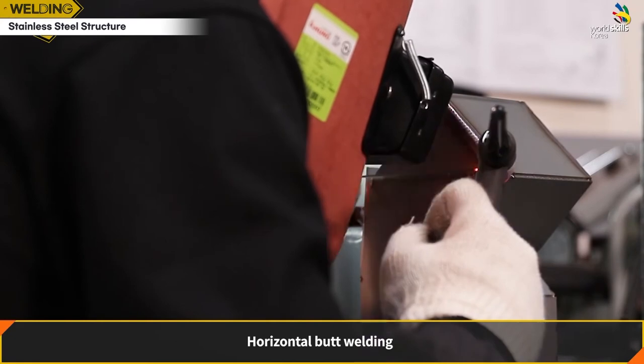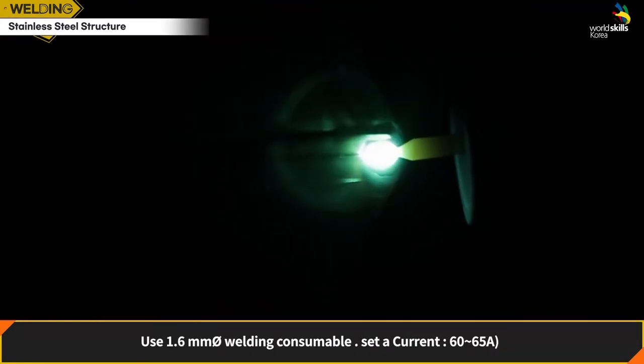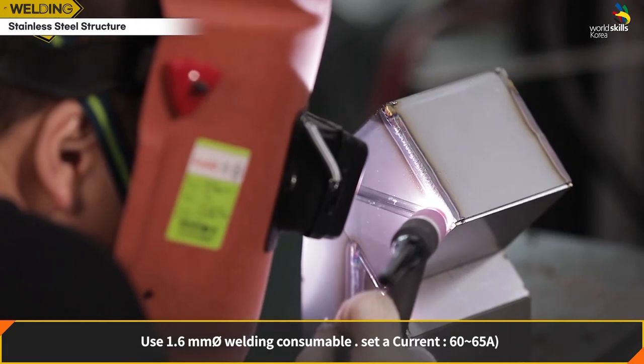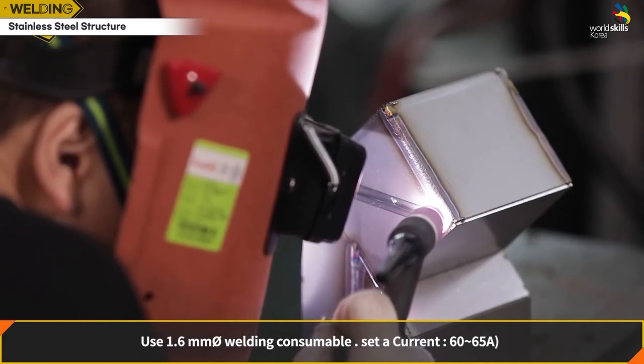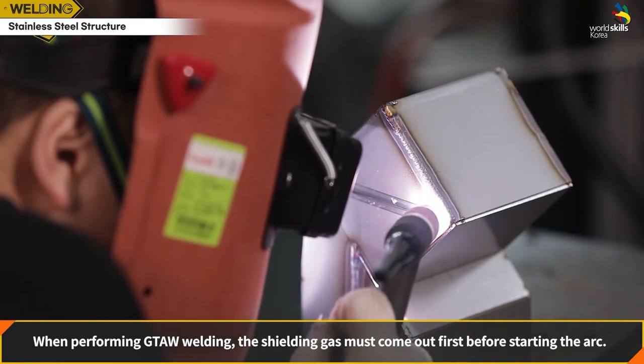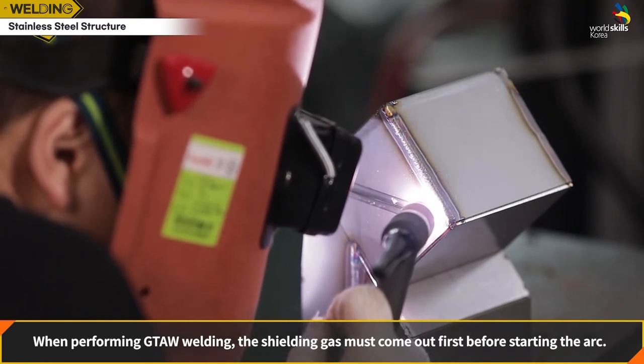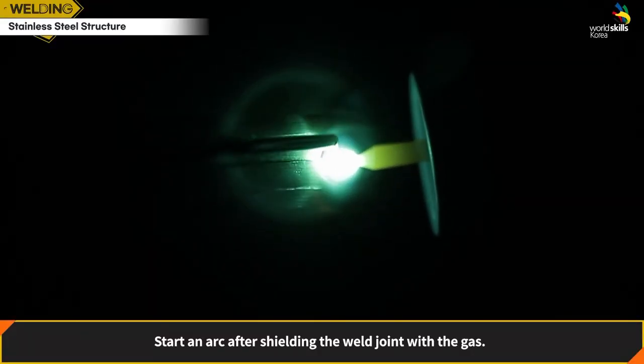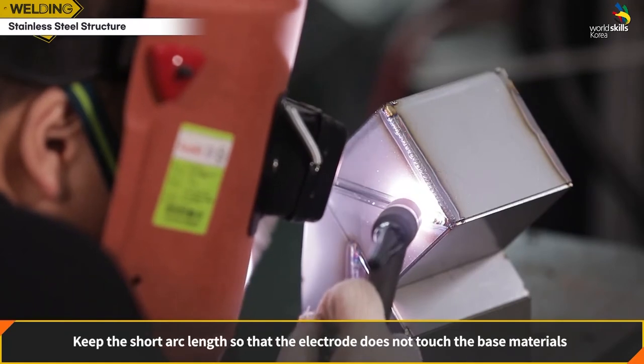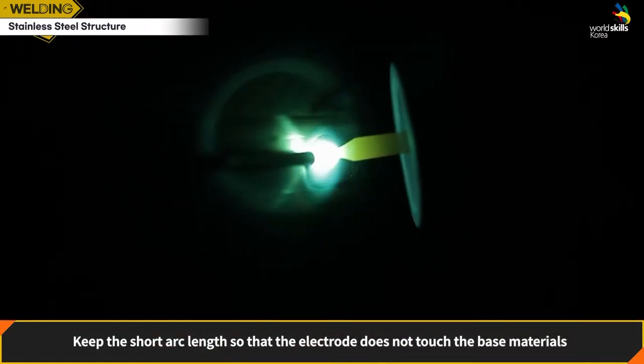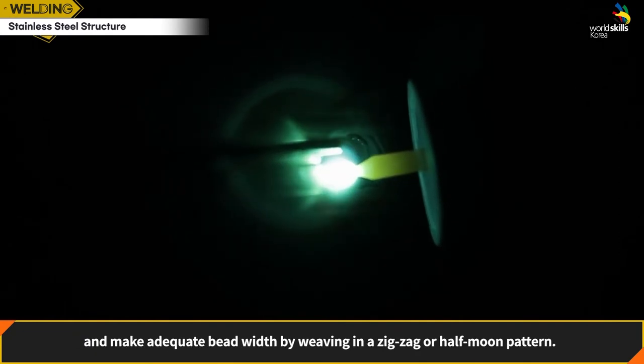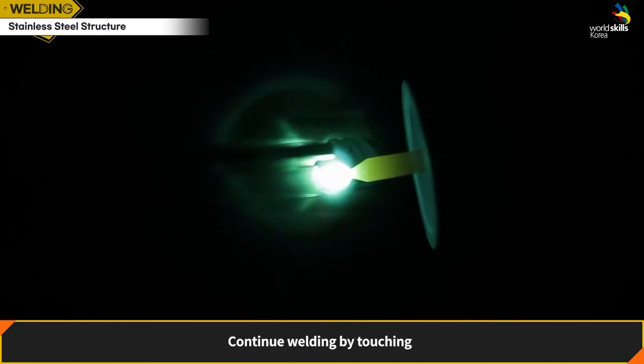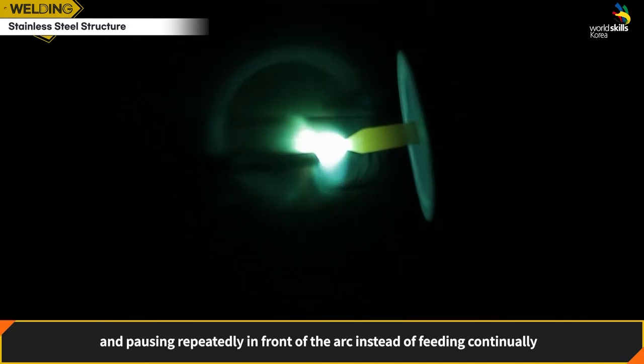Horizontal butt welding. Use a 1.6 mm welding rod and set the current at 60 to 65 ampere. When performing GTAW welding, the shielding gas must come out first before starting the arc. Start an arc after shielding the weld joint with the gas. Keep the short arc length so that the electrode does not touch the base materials, and make adequate bead width by weaving in a zigzag or half-moon pattern. Continue welding by touching and pausing repeatedly in front of the arc instead of feeding continuously.